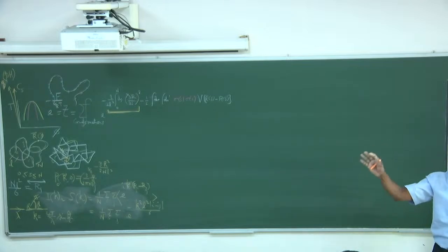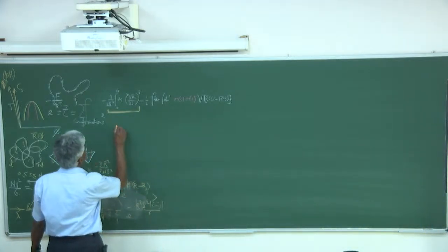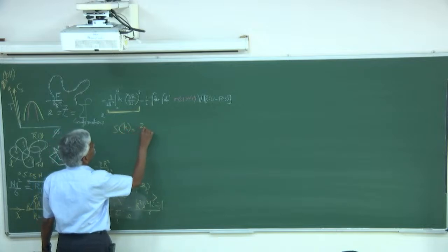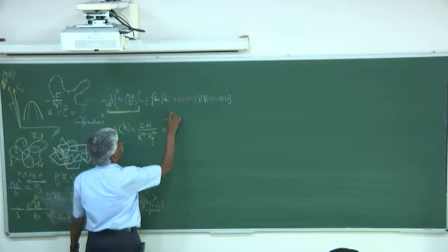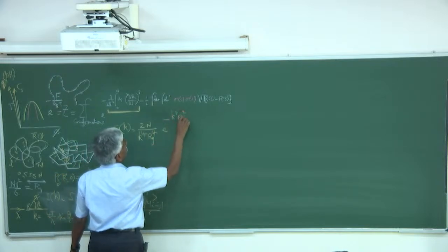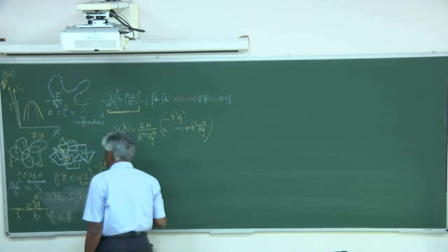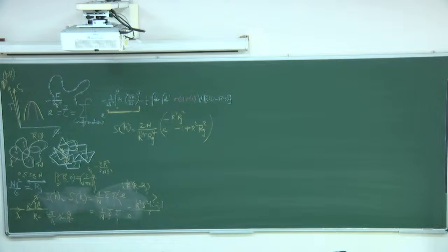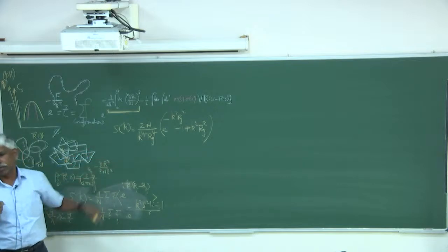How do you get this from here? Because this is a very famous formula and it is loaded with information. And this in fact makes the principle of experimentation. The way biopolymers or synthetic polymers are characterized is using that expression. That's the theory and this is the experiment. Even Debye was also a great experimentalist, right? So he would do this experiment and this theory, match these two and then determine everything. He will determine the molar mass of the polymer, how big the number of monomers N is. He will also figure out Rg, because N appears here, Rg appears here.